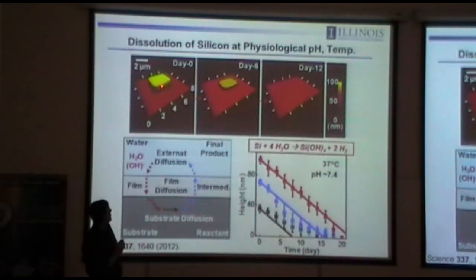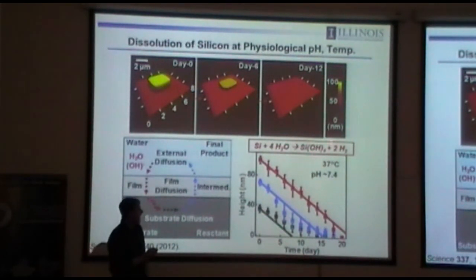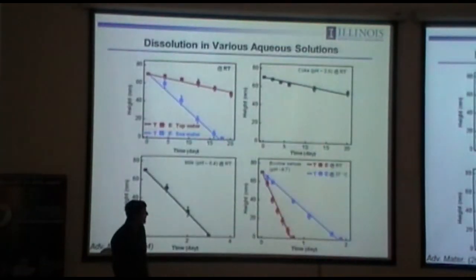And you can see here's AFM, day 0, day 6, day 12. That 2 nanometer per day begins to be significant. You etch all the way through, the silicon is completely gone. And by the way, silicic acid is naturally occurring in biofluids and in groundwater and seawater, so it's fully environmentally and biologically compatible. And we stumbled across this, immediately recognized that's pretty powerful, because if you could do water-soluble electronics with silicon, immediately you could do a lot of sophisticated things in terms of devices. And you can do that.